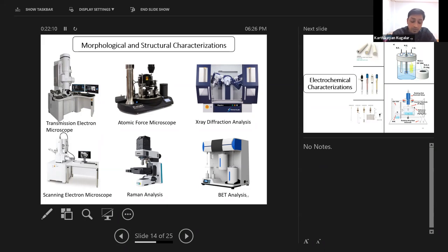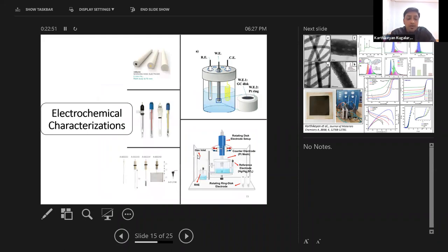And the atomic force microscopy has a cantilever which will be moving over the sample, and depending upon the sample surface, the cantilever will be deflected upward and downward. Based on the movement of the cantilever, you will get the images. These images will be used for the characterization of the morphology of the sample. And the Raman analysis and the X-ray diffraction analysis will be used to understand the solid state chemistry. And the BET analysis will be used for calculating the specific surface area and also the pore size distribution in the sample.